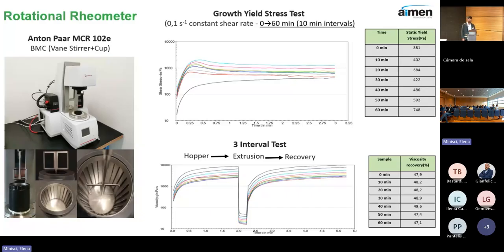First one is the static yield stress test. Here we apply to the sample a very, very low constant shear rate, and we obtain a maximum, which is the static shear stress. This stress is the pressure that we have to apply to our cement in order to start the flow. We also analyze the evolution of the shear stress over time. And the second test is even more interesting because it simulates the 3D printing process. It's called the three-interval thixotropy test. Here we have three regions of shear rate.